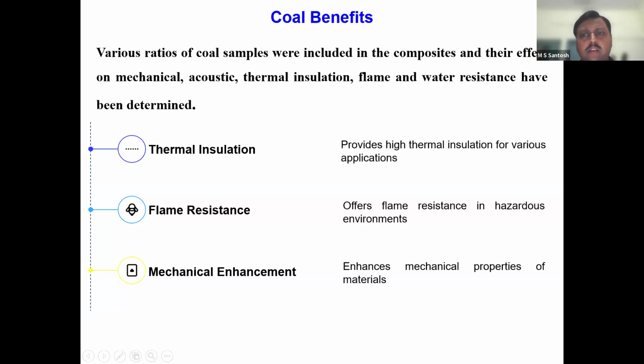When you look at the coal samples being used as composites, we have specifically focused on the mechanical, acoustic, thermal insulation, and flame and water resistance properties of these materials. Specifically for thermal insulation, we focus on the various applications, followed by the flame retardancy exhibited by coal-based composite materials, and the mechanical strength that it can offer to the biomass-based composites. Because coal being a harder material, it has the ability to increase the strength of the biomass when blended with it with a suitable binder.